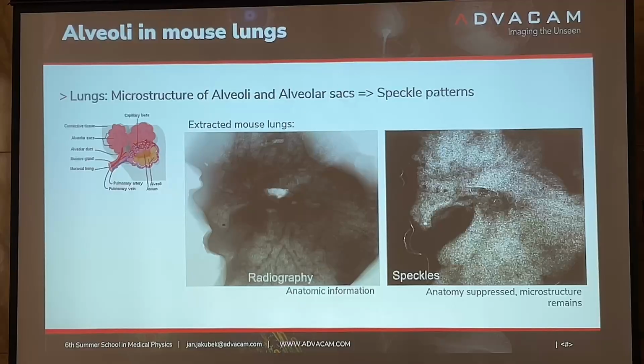We performed a nice experiment with mouse lungs. Because lungs have this alveolar structure inside, so it's like small bubbles, and they can act as lenses. Behind these alveoli, at a certain distance for a certain energy, you would start to see this bright spike in the middle. You have to always find the right distance and select the right energy, and then you see it. If you don't do that, then all the energies would overlap and you would not see anything.